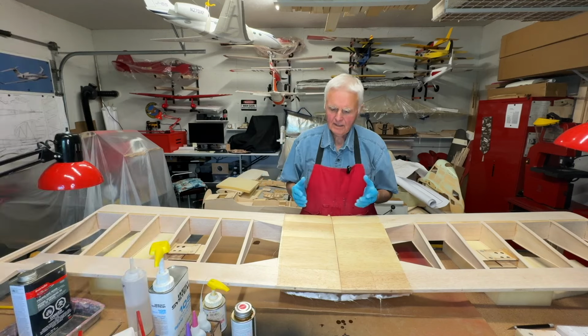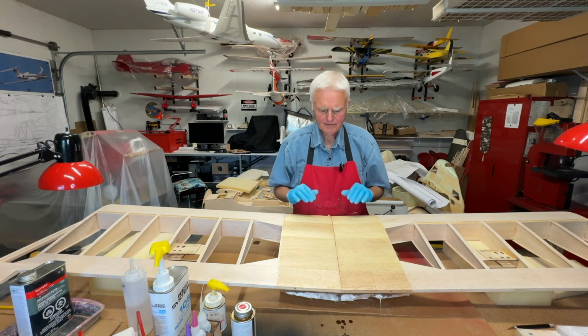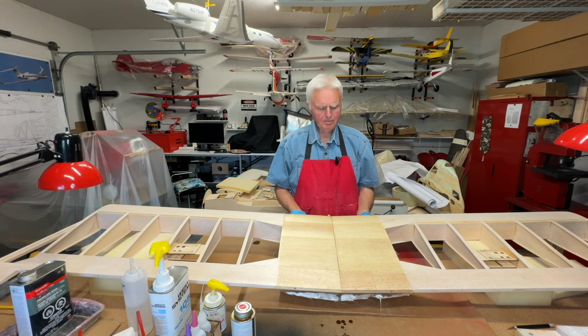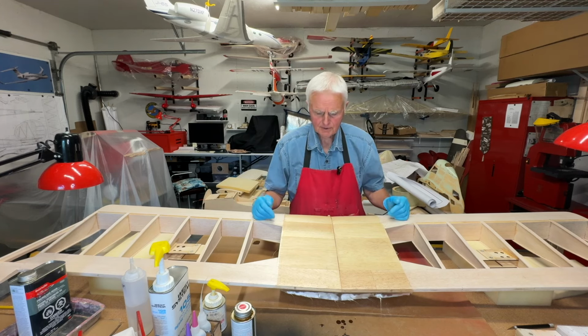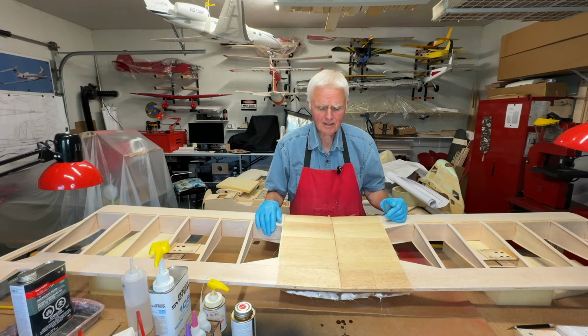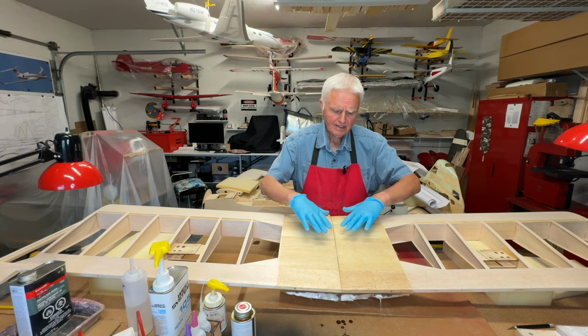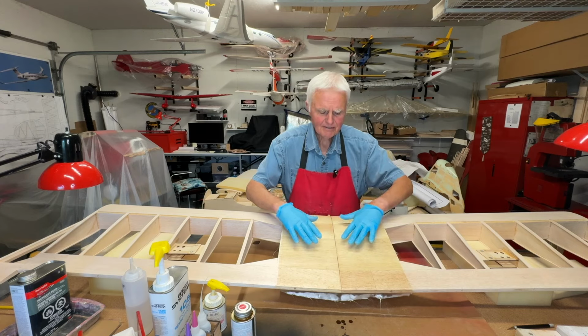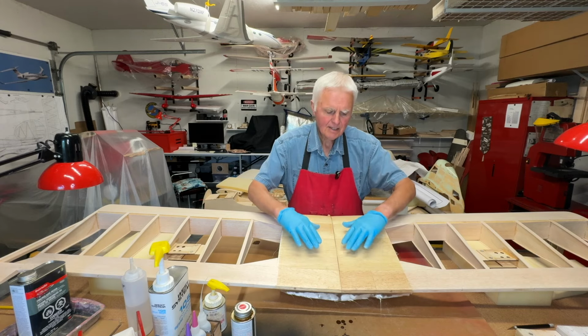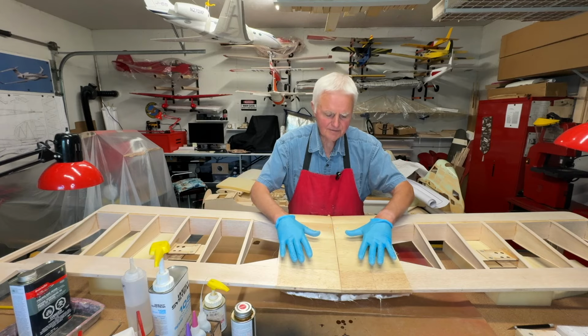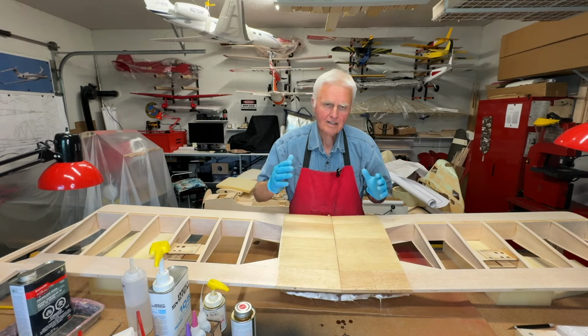Now the top surface has been finished as well. Previously we did the bottom surface, which has cured overnight. And the top surface was applied exactly the same. It's basically one coating of epoxy resin. And as you saw previously, the excess resin that stays on top of the fiberglass cloth, after it's soaked into the fabric, gets removed.